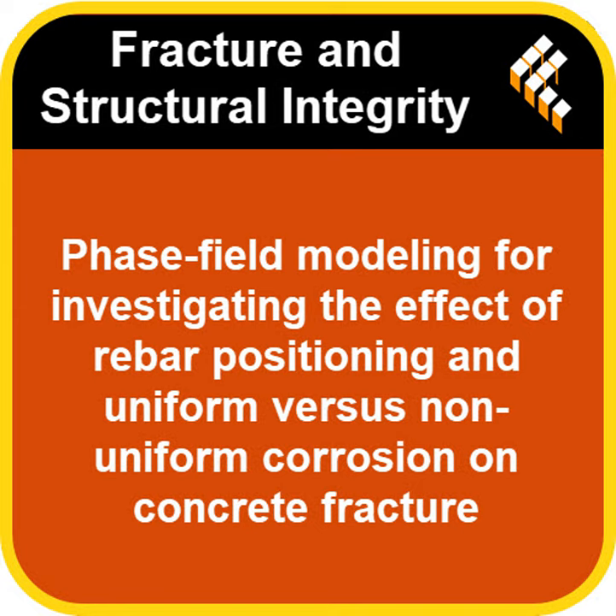Exactly, cover detachment. And the amount of rust expansion needed at T1 and T2 was also pretty similar between the uniform and non-uniform cases for any given cover thickness. So putting them in the corners seems to maybe make the type of corrosion less critical for the overall pattern. It seems that way for the specific corner arrangement, yes. The geometry dominates, perhaps. Okay. But what happened when they moved those same 4 rebars to the middle of the edges?